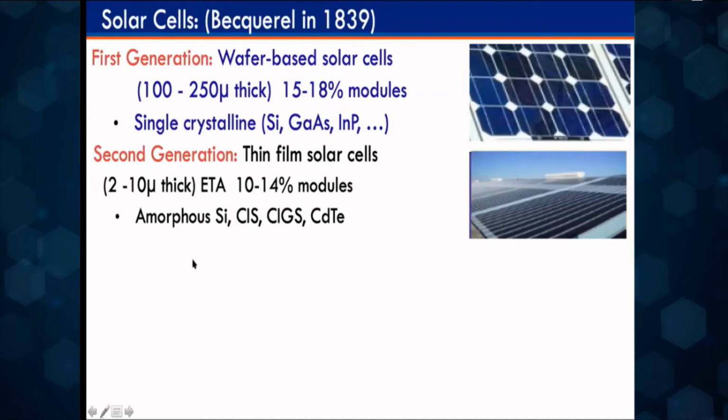But amorphous silicon suffers from a major problem, something called the Staebler-Wronski effect. Again, this is very well known in the field. When I say Staebler-Wronski effect, for those of you from an inorganic chemistry background, you see there's a silicon-hydrogen bond. When you keep shining a light on that, you kick out the hydrogen, you break the silicon-hydrogen bond, and the lifetime of the solar cells dramatically goes down compared to the first generation. So this is a persistent problem in the field, and people did not manage to come up with a good solution for the Staebler-Wronski effect.